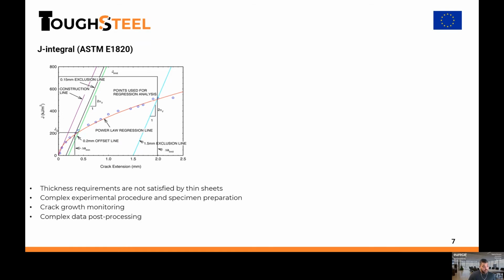But this means that these thin sheets are in plane stress, which means that all this fracture energy has an important contribution to the out-of-plane deformation or local necking. Then all these fracture toughness parameters in thin sheets under plane stress conditions depend on the thickness. So this is important to keep in mind when we're talking about all the fracture toughness parameters that we will see today, and about plane stress fracture toughness in general: these toughness values depend on the thickness. So it's not a material property itself, but a constant for a given sheet thickness.